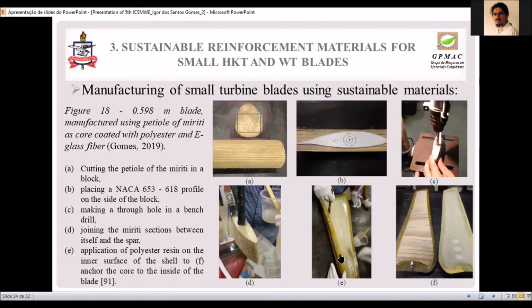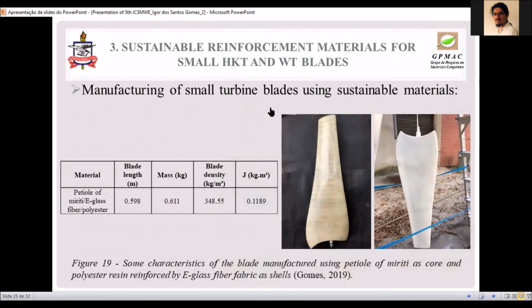And at the end, we apply the polyester resin on the inner surface of the shell to anchor the core of the blade, and then close the blade to cure the polyester resin. In this figure, we see the blade manufacture. After the resin cured, the irregularities in the leading edge and trailing edge were corrected. Also in the root and the tip, this was carried out using polyester putty and sanding. And we see here also a metallic insert with a drill hole to make it possible to fix the blades to the hub of the turbine.